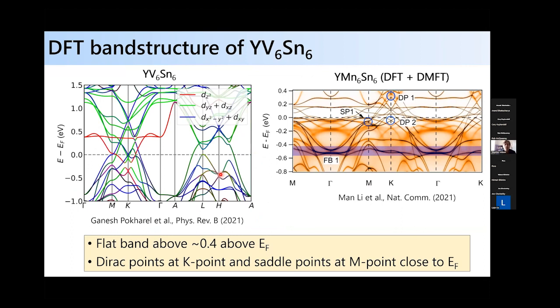And if you look at the band structure, let's look at the non-magnetic version, yttrium vanadium 6-1-6. This is just from DFT, showing the contributions at the Fermi level, which predominantly come from the vanadium ions in the kagome net. You can see that the filling is rather close to some of these Van Hove singularities near the M point. The filling is also close to the K point Dirac crossing in these systems. And then there was some discussion in the previous talk about DFT plus DMFT band structure calculations for the manganese variants. It's not dramatically different, but the vanadium system is non-magnetic, so perhaps it makes life a bit easier.